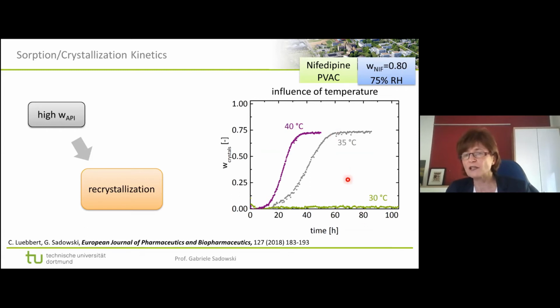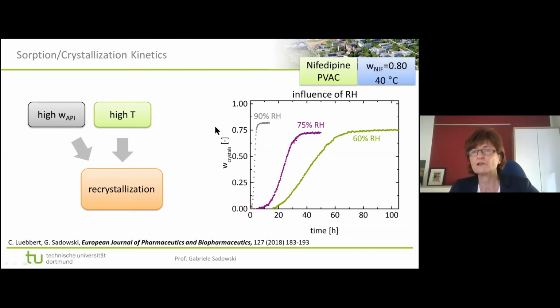So the lower the temperature, the more we are away from Tg, the better. So temperature is really a huge factor, and lower temperatures are much better than higher temperatures. And then most interestingly, we investigated different relative humidities.